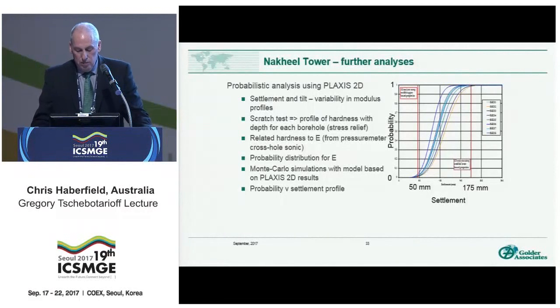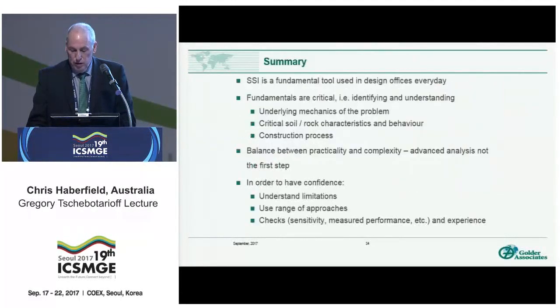This was then calibrated with the modulus of the ground as assessed from the pressuremeter and cross-hole seismic testing, and a probability distribution for Young's modulus developed. A simple analytical approximation to the stress distributions below the piles was then developed and used in Monte Carlo simulations carried out within a spreadsheet. From this, the probability versus settlement profiles at each borehole, as shown here, were calculated, and the design team considered the probability of the tower experiencing unacceptable settlement or tilt was very low.